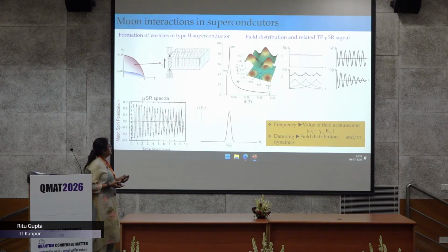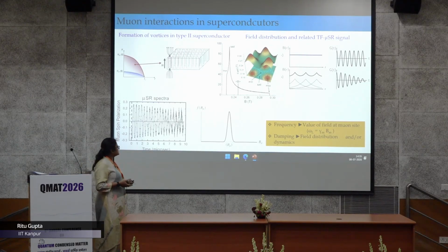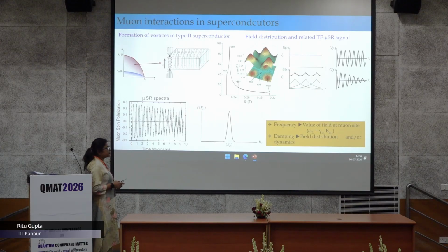lattice in your material. And as I said, this muon spin polarization as a function of time is what you see in a muSR experiment. If you take the Fourier transform of this, it will tell you about the field distribution. If it is a paramagnetic state, you will not see any damping, because your muon is experiencing only one field, whatever you apply from outside. So you will see a very sharp peak.